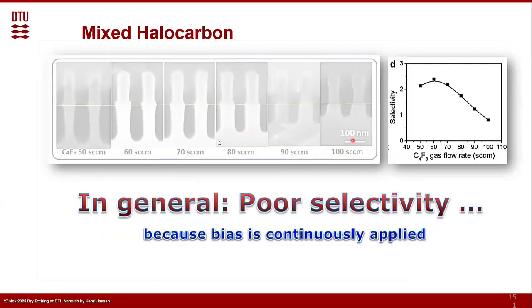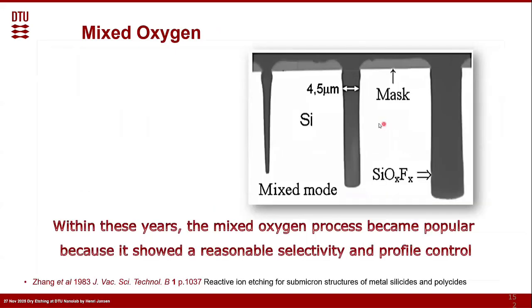The reason is that the bias in this mixed process is all the time there. You can see that the selectivity between maybe photoresist and the silicon is maybe up to 2 or so. So silicon can only go 2 times faster, or the oxide is going 2 times faster than the resist as a mask. And they could improve that by processes where there's less deposition of inhibitors, so you're a little bit more to the point. And then the mixed oxygen process, so that's SF6 mixed with oxygen, became quite popular. And it showed already a reasonable selectivity, as that can go up to 20 or so easily.